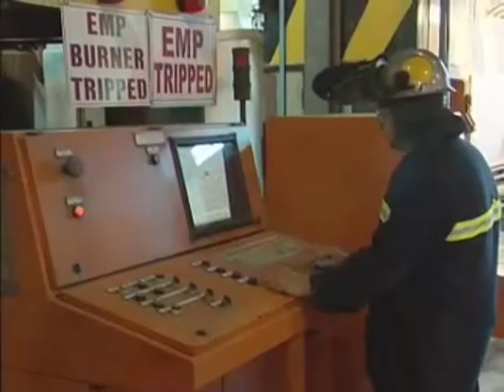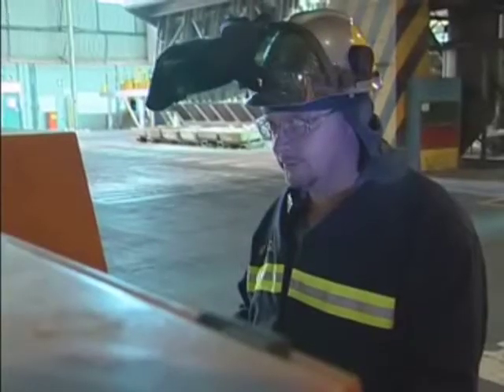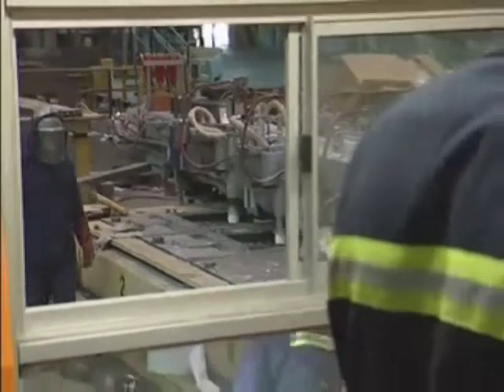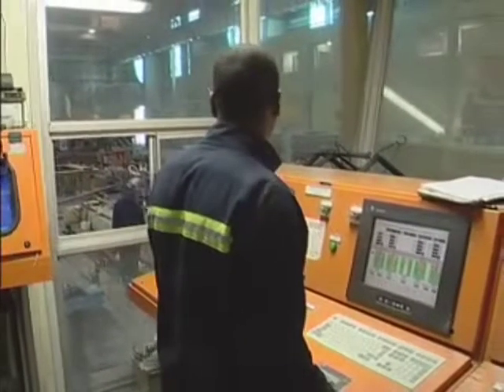In terms of other issues, the more metallurgical type and metal cleanliness issues, I think we've got a good process anyway, in terms of our metal cleaning operations, if you like. But definitely we've seen in the melting furnace itself a reduced quantity of magnesium oxide, which comes from alloying magnesium, burning and things like that. We've seen a significant reduction in the burning on the surface of the melt in the melting furnace. And clearly the benefits of the pump are that the magnesium bar gets submerged almost immediately, and we get very good dissolution in the EMP well itself, and eventually pump it out through the bulk of the bath. And as I said, we've got some techniques which we use, which we can consistently get above 98%.